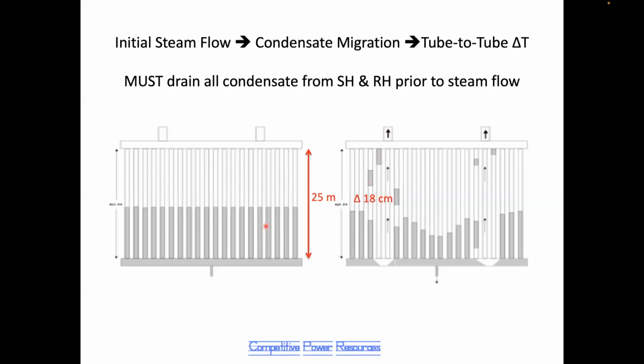So they have expanded, and this header will have moved downward several centimeters. When these tubes have steam in them, those tubes suddenly cool by 50 to 150 degrees relative to their neighbors that are still at 550. So these tubes shrink and cause the fatigue damage that we described in the previous slide. To avoid this, it's critical that the superheater, and everything I say about the superheater also applies to the reheater, be drained. This water must be drained out before steam flow is permitted to begin.